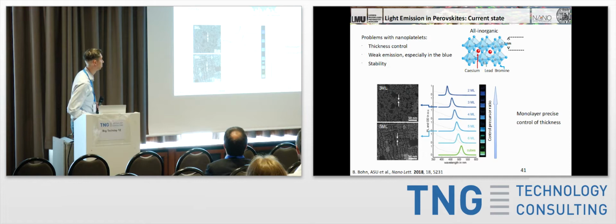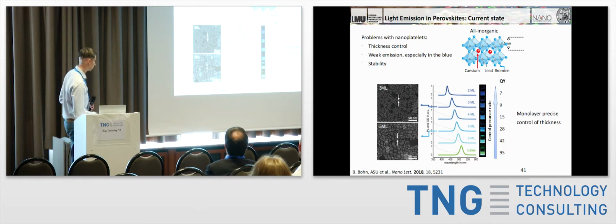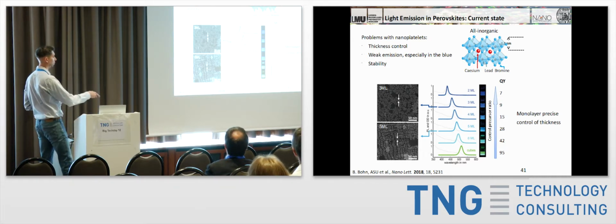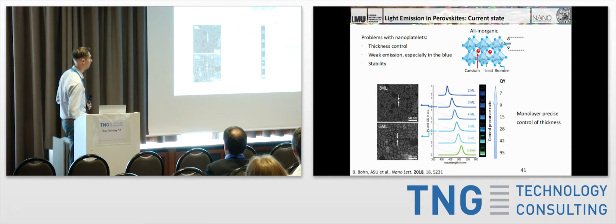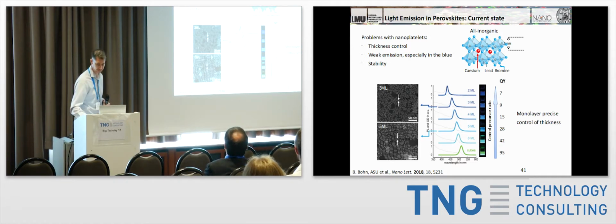And essentially what we're able to do now is control the thickness of these platelets with a single monolayer precision, so from 2 monolayers, so just over a nanometer, to a little larger, to cubes, and so can really nicely tune now the emission color of these nanocrystals. Again, the quantum yields, though, suffer from that. So the cubes that we're able to produce have a quantum yield of about 95%. As you can see, as we go thinner and thinner and thinner, they become worse and worse.